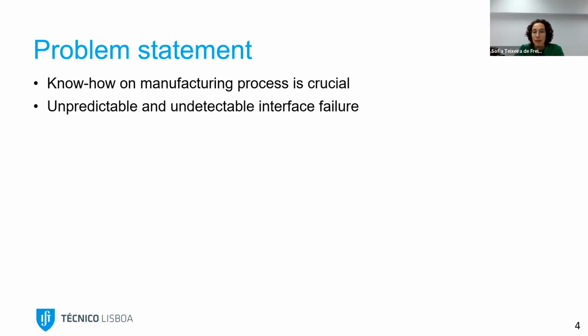Another challenge is that nowadays interface failure is undetectable. It is quite unpredictable. What is an interface failure? An interface failure is what we generally call a kissing bond, which means that you have the two substrates and the polymer joined together. Looking at it by the visual eye, everything seems to be integral with no defects. However, when you start to detach both surfaces, there is really no strength in it. There's a contamination on the surface, for example, or something went wrong in the quality of the manufacturing, and that creates an interface failure.